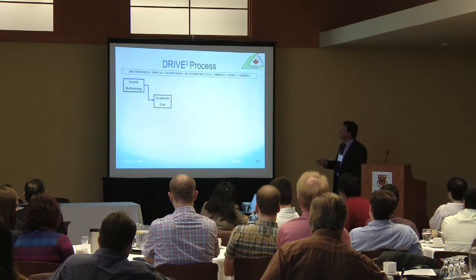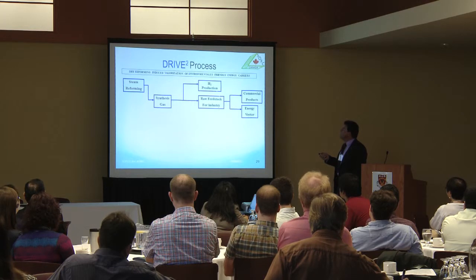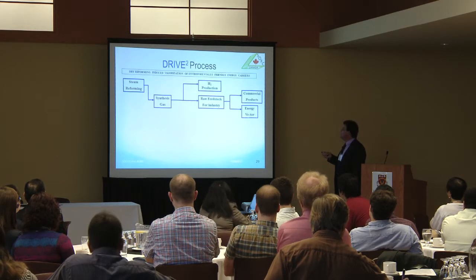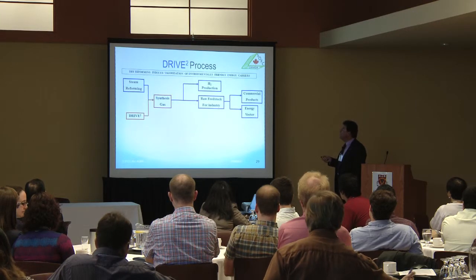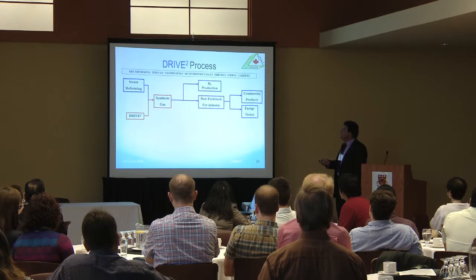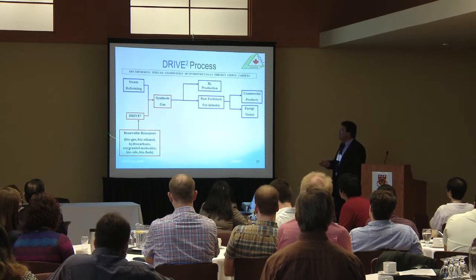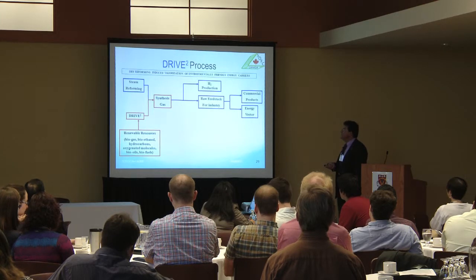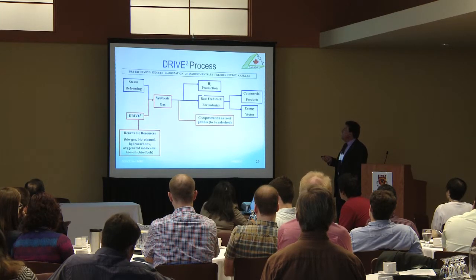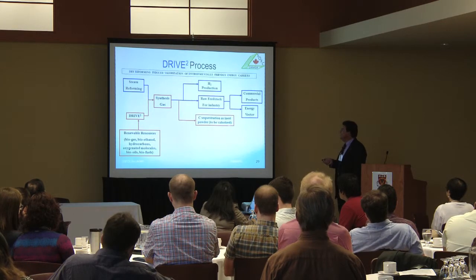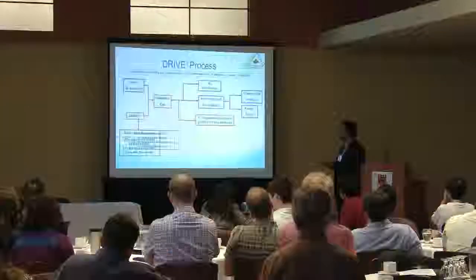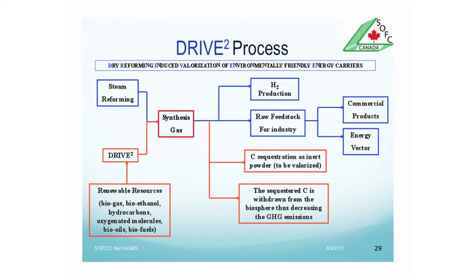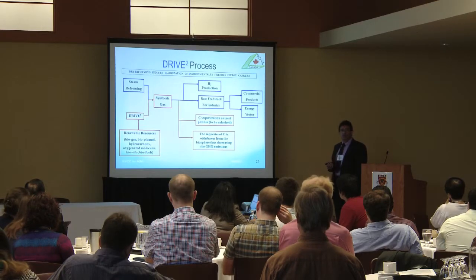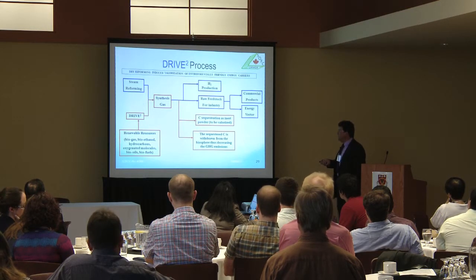We have steam reforming producing synthesis gas. This synthesis gas can produce hydrogen, can be raw feedstock for industry, can go to commercial products or serve as an energy vector, for example, for fuel cells. If we add dry reforming, we can also get synthesis gas, but at the same time, we can get it through renewable resources or dry reforming from different renewable resources. This not only produces the hydrogen but also does carbon sequestration as an inert powder, which can be valorized. And valorization is done through the work I have presented. And this sequestered carbon is refractory, cannot be oxidized. And if we don't burn it at very, very severe conditions, then it is withdrawn from the biosphere, decreasing the emissions.